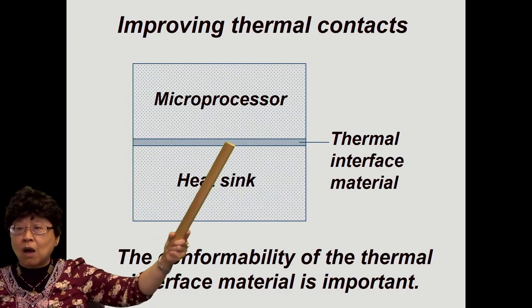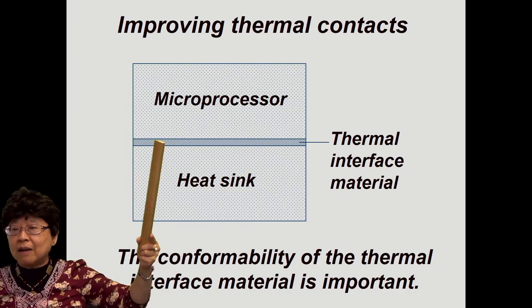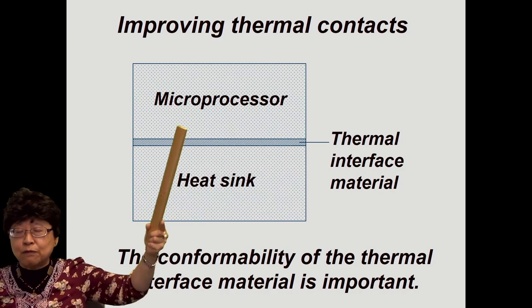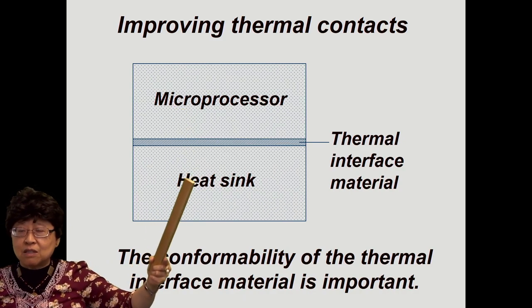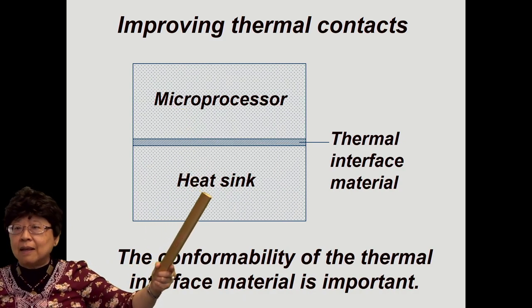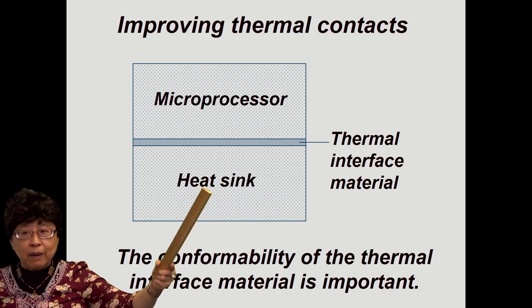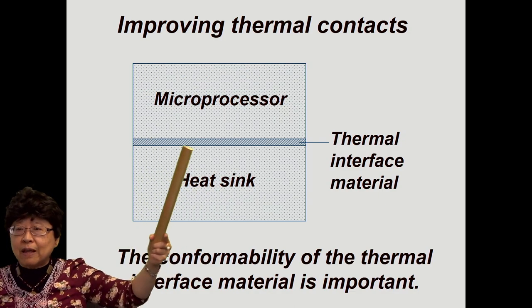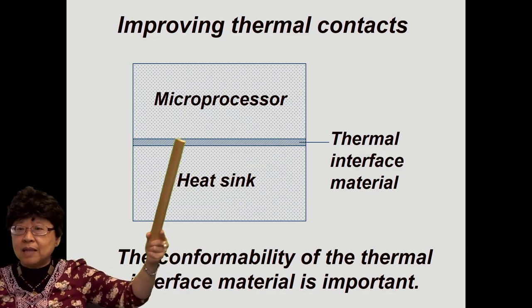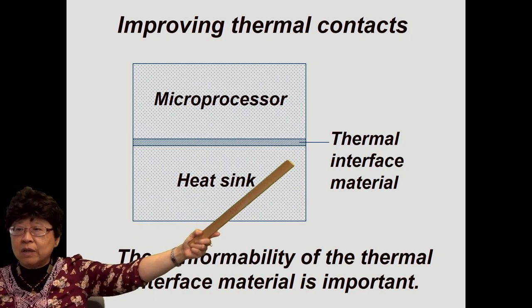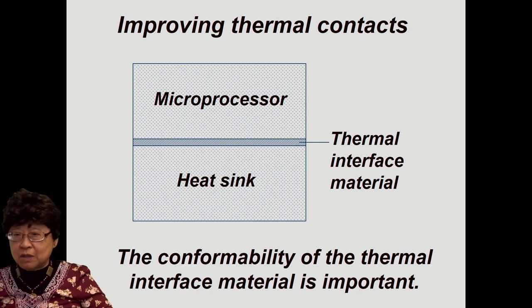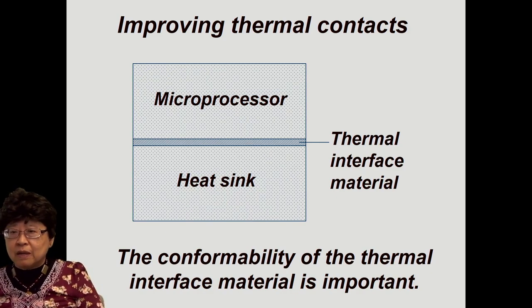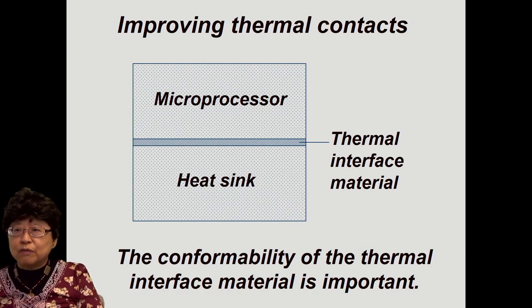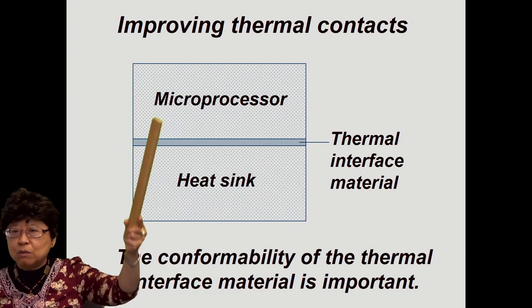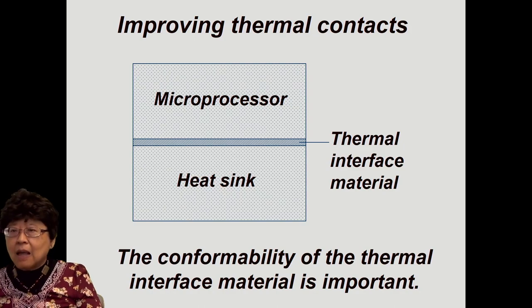If this thermal contact is bad, you are not getting the heat to flow from the microprocessor to the heat sink very well. Then you're not utilizing the heat sink very well. Okay? And to improve that thermal contact, one puts into this interface a material called a thermal interface material. Now, this material needs to conform very well to the surface topography of these two mating surfaces.